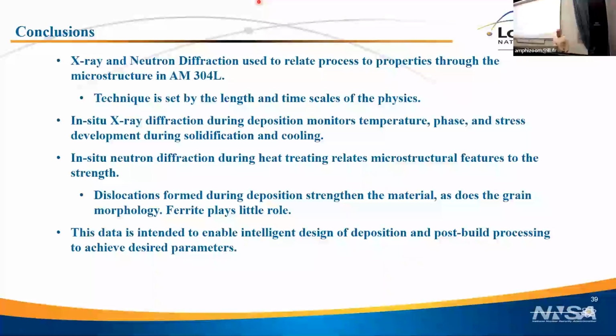So the first additive manufacture measurement we did with Livermore was in about 2013. We worried about that. It was on a stainless steel part, and we took out D zeros along the whole length. Saw no effect. And that gets back to my statement that nickel, chromium, and iron have almost the same metallic radius. So you wouldn't see an effect there, even if the chemistry did change.